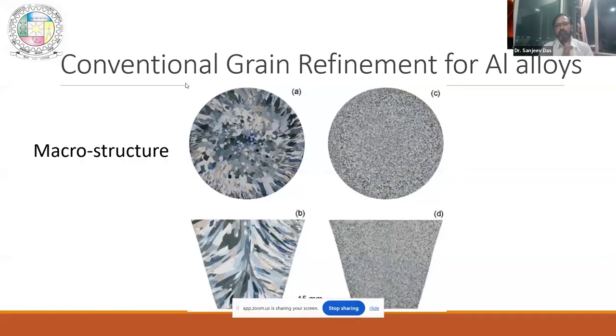When you add the grain refiner, if you can see A and B, these are basically without grain refiner. You can see the bigger grain structure. This process is basically the TP1 test. I will show you some schematic later, where we basically measure the grain size of any metal. So you can see the bigger grains, and when you add grain refiner, you will see the fine grain structure. And there is an equation called the Hall-Petch equation. Metallurgists may know it, it's very familiar. If the grain size decreases, the strength increases, irrespective of your chemical composition or alloying or anything. So that is the beauty of grain refiner.